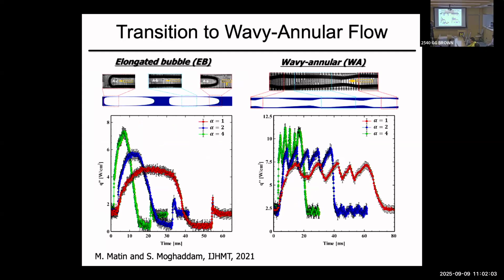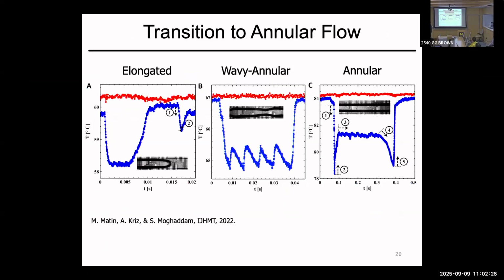When you start moving into higher inertia fluid, way past the regime that we talked about, you start getting into wavy annular flow, where you get these ripples over the surface. They have different characteristics. We published a paper on that with different aspects of it, discussed and mapped. And then you go from there to the annular flow, where, again, we published a paper, and we differentiate what we are seeing, why we are seeing it, and what the implications are for what people see in heat sinks.